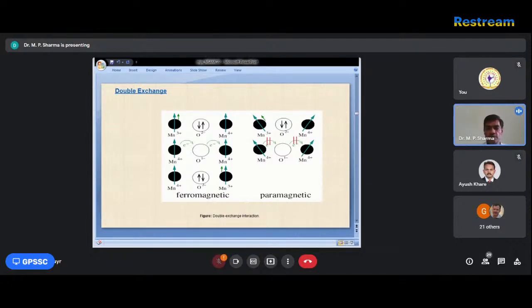So if the d electrons of the two manganese ions are parallel, the configurations of Mn3+ oxygen Mn4+ and Mn4+ oxygen Mn3+ will be degenerate, and that gives the ferromagnetism. In the same case, but where the spin is canted with some angle, the resultant also gives the ferromagnetism.